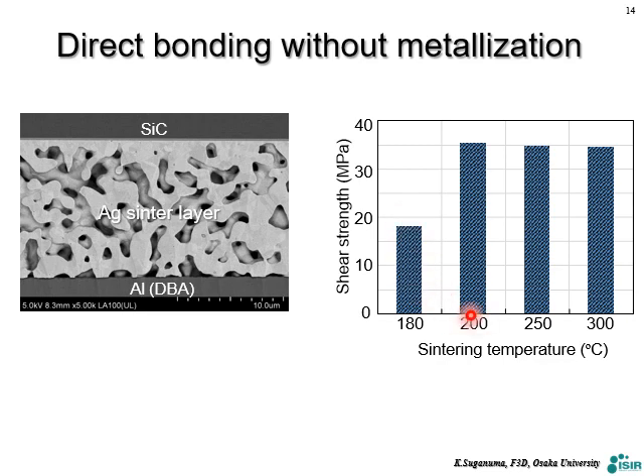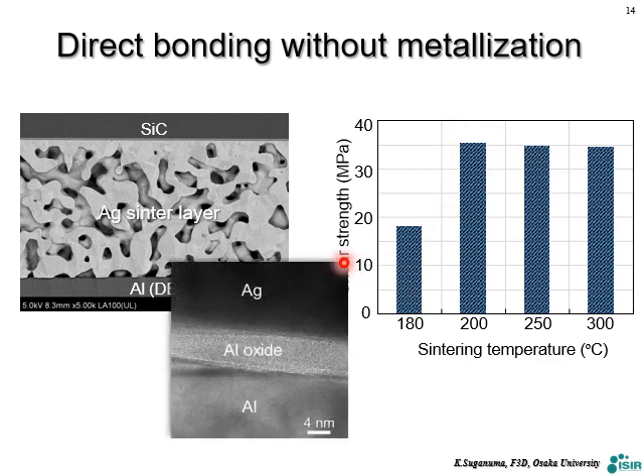But beyond 200 degrees C, the strength reaches 35 megapascal. This is good news. We don't need to increase the temperature, so 200 degrees C is one of the best choices. And it is very strong. So we can make a good joint, good bonding onto aluminum.